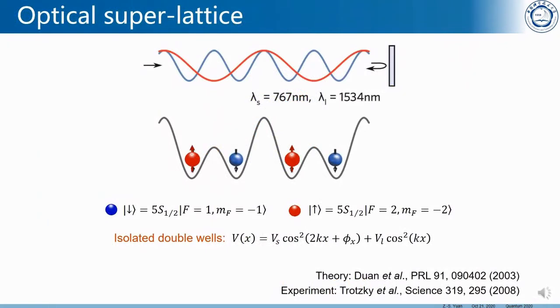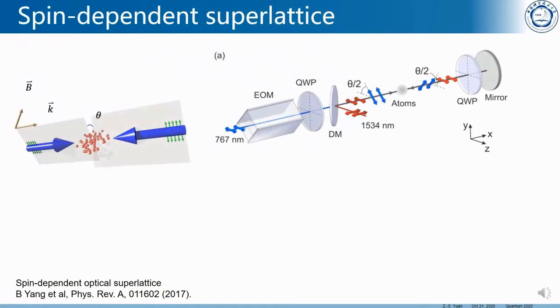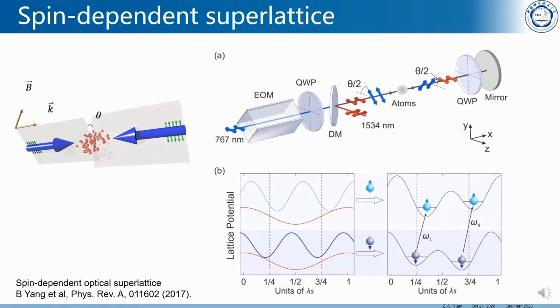The superlattice is formed by overlapping two laser beams with wavelengths of 767 nanometers and 1534 nanometers respectively. And the spin states are defined by two hyperfine split states of the rubidium atoms. In order to operate every second site in the lattice, we develop a new technique called spin-dependent superlattice. Different from normal superlattice, we rotate the polarization plane of the retroreflected beam of the short lattice. Therefore, the two species of the spins experience different trap depths in the double well, as shown in the figure.